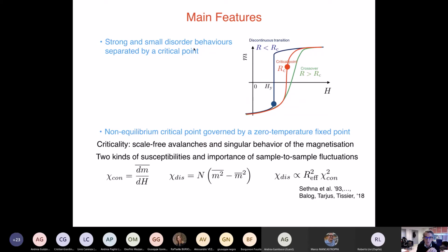So, for example, the curve that I'm showing you, even if it's a sketch, is what you find doing the mean field theory. The main feature that you find is that there is a clear difference in behavior depending on whether the disorder is strong or weak. If the disorder is strong, which is the green curve that you see in the figure on the top right, you find a smooth behavior for the magnetization, which starts from -1 when H is very negative, and then smoothly goes to the value +1 when H is very positive.